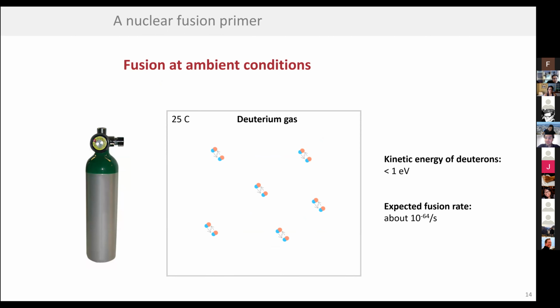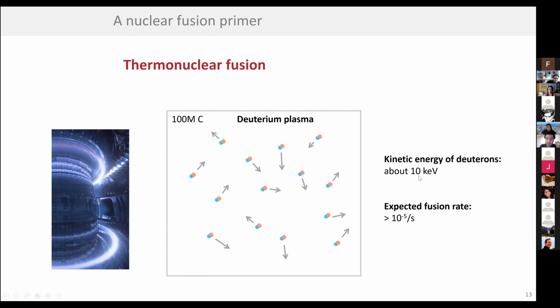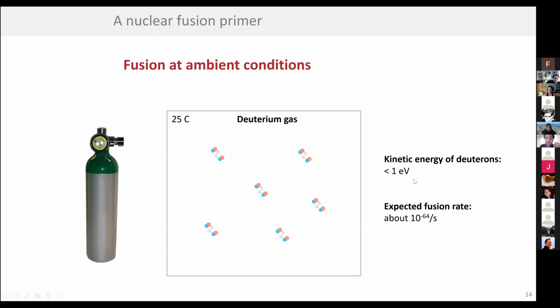And so the other extreme would be to look at: can you have fusion in a gas bottle? So if you go buy one of those gas bottles at Target, actually no, you can't get those at Target, but with hydrogen gas from a supplier, then you have deuterium or hydrogen molecules in there. If you buy normal hydrogen gas, I think it's 0.02% of it that is going to be deuterium, but you can also buy the deuterium by itself. And so you have these molecules and pairs of deuterium atoms, and the kinetic energy for them would be equivalent to about 1 eV, because they wiggle around a little bit. Again, if we go back to our fusion plant, it's 10,000 eV, so we have much less energy between them.